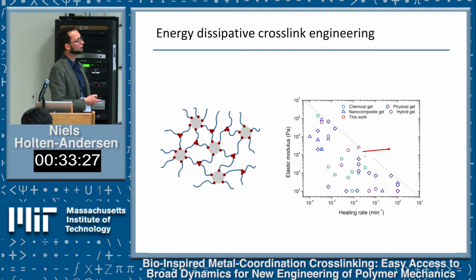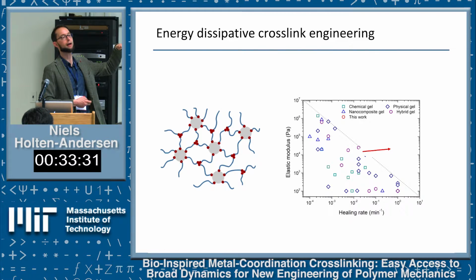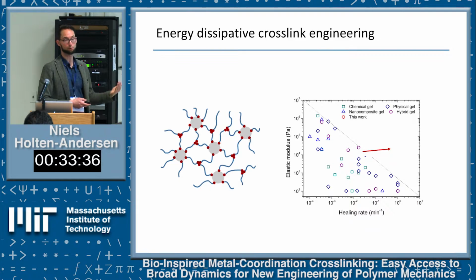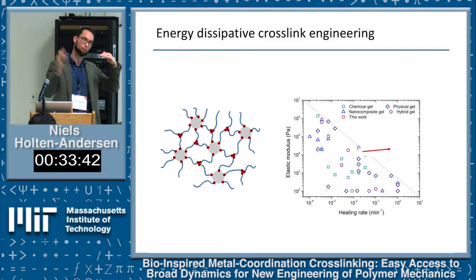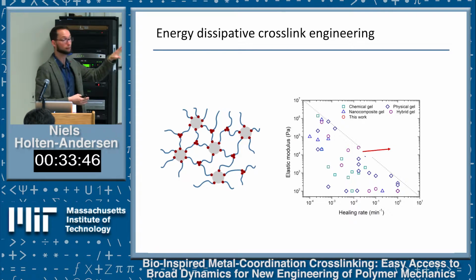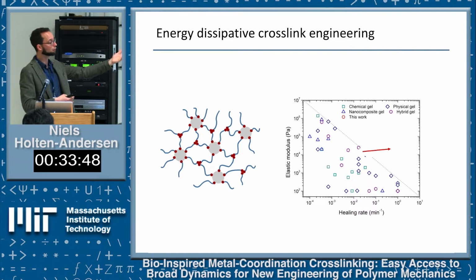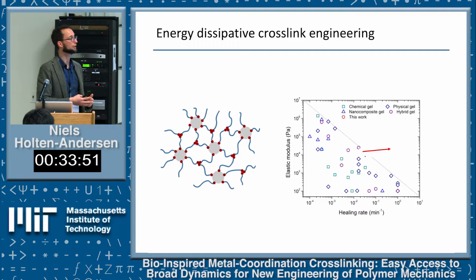So the real challenge is, can we actually begin to keep the stiffness of the material high and still speed up the recovery? That's exactly what this class of material is beginning to do. By having a certain amount of nanoparticles, we keep the strength up, but the more metal ions we add, the quicker they become at self-healing. We're trying to understand the underlying physics right now, but at least so far the data seems to suggest this is a step in the right direction of engineering both strong and self-healing materials.